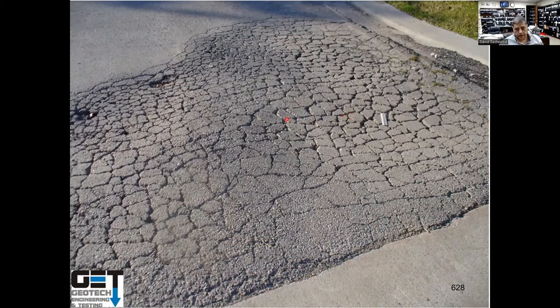Another question. What's the recommendation for concrete cylinder tests that come back at 2000 PSI at 56 days break? It's a large driveway and it may be hard to determine the extent of the bad batch. It was specified at 3,500 PSI at 28 days. So if you're supposed to have 3,500 at 28 days and at 56 days you got 2,000, your concrete fails. They have to demolish it, take it out, and put new concrete in.